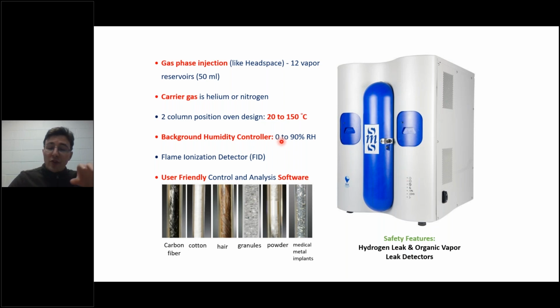Much like we saw with dynamic vapor sorption, the influence of humidity can have a really large impact on uptake, as we saw with the gravimetric method, but they can also have a significant impact on the surface properties of our sample. So we can measure the influence that humidity would have on the surface area and on surface energy. And the way we do that is by committing one of these reservoirs to water. So I can now do an experiment with a constant humidity background. So I can find out my surface area, I can find out my surface energy as a function of a constant humidity there throughout the experiment.